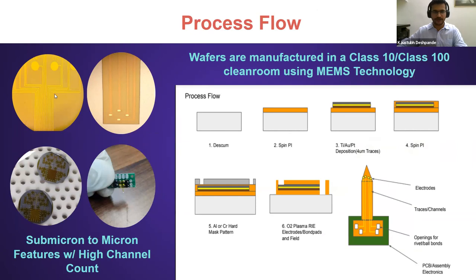So when we draw out the CAD model, we spin coat a photosensitive polymer on a wafer and then expose it through a mask. So with this, you're able to put designs and have thin film designs be stacked onto the wafer. This is an example of liftoff where you could put down metal and put down thin film traces, which are used for traces and recording electrical data.